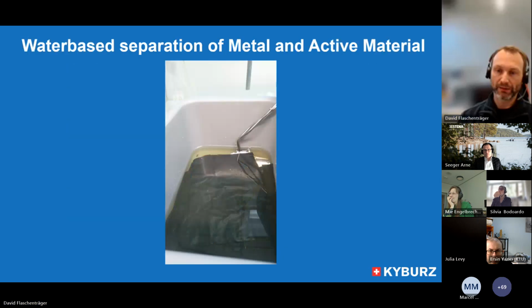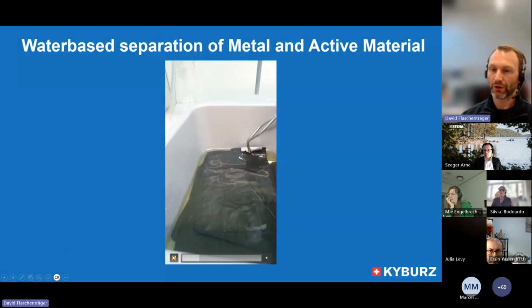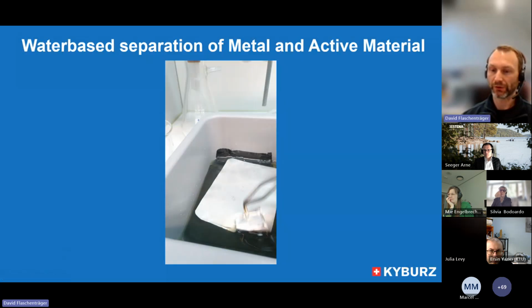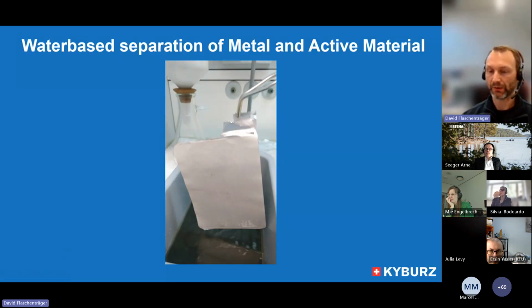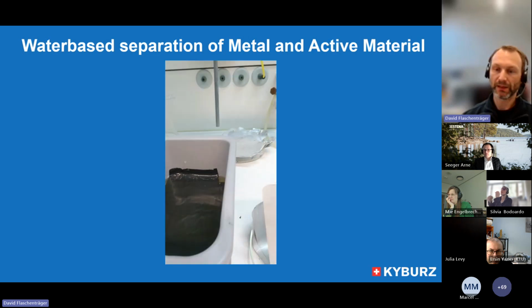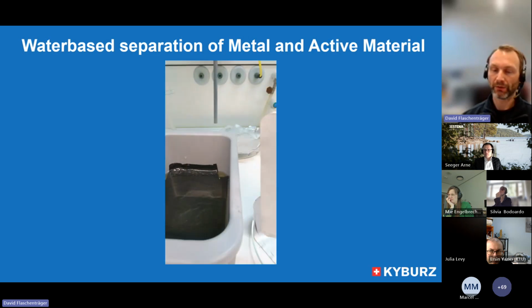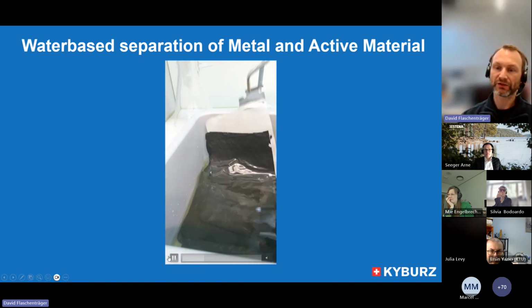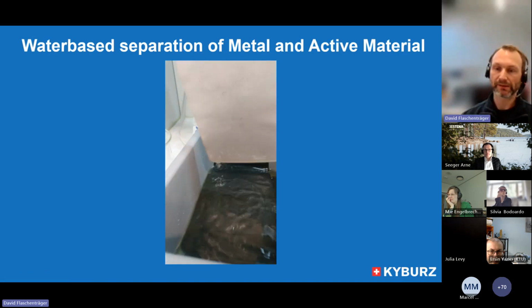And in the next very short video, we show what happens if you immerse these electrodes, being anodes or cathodes, depending on the cell chemistry and the binder system, in a solvent. In our particular case, it's deionized water, but in some cases we have to use other solvents. And as you can see, quite quickly, you can simply detach the coating from the current collectors.